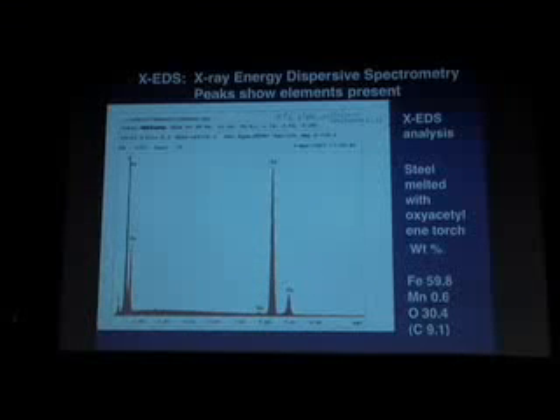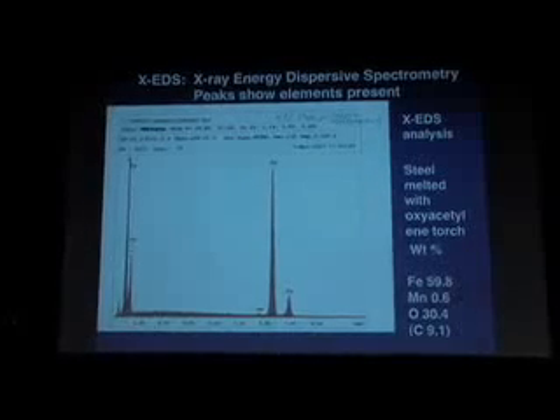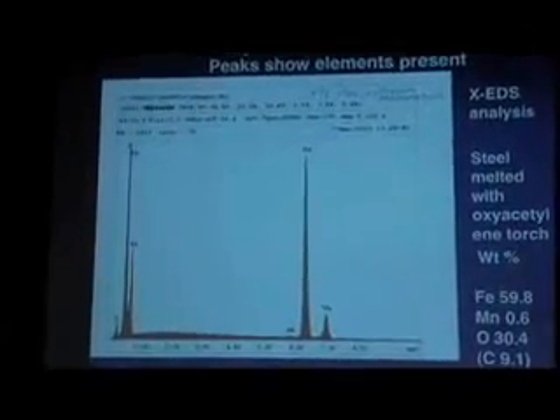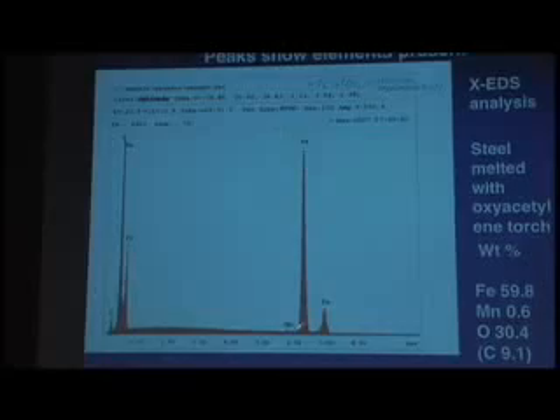Now, what is going on? What generates these peaks? Well, the electron goes into the material that you're analyzing, and it excites the atoms, gets them all revved up, and then they emit X-rays of a characteristic wavelength, or energy is what we're looking at here. And so it's like interrogating, asking, without damaging, by the way. The electrons go in, excite the atoms, and then individual elements will emit a characteristic pattern of X-rays. So with iron, you see these three peaks. And you say, aha, there's iron. And the analysis code then tells you approximately how much. About 60% in this one.